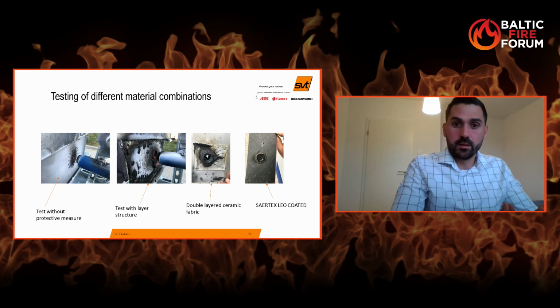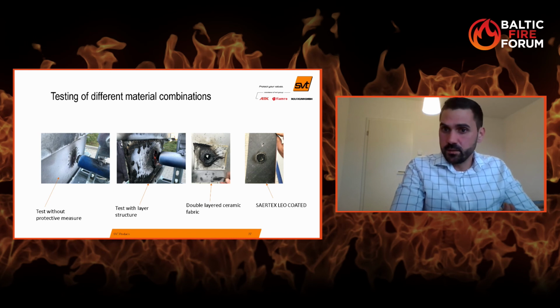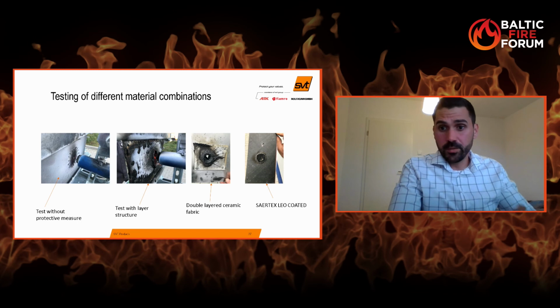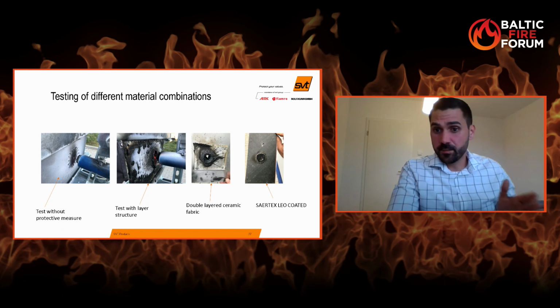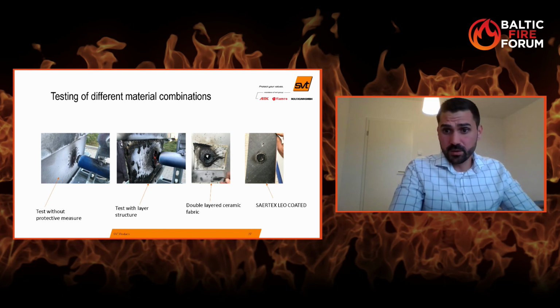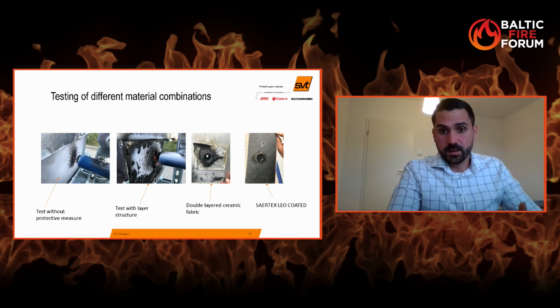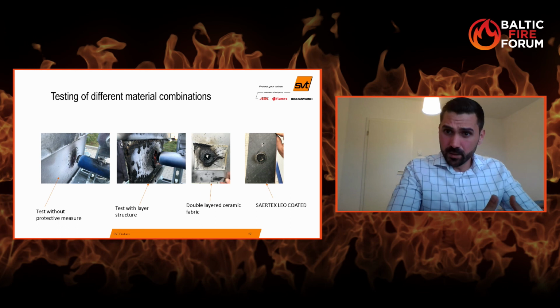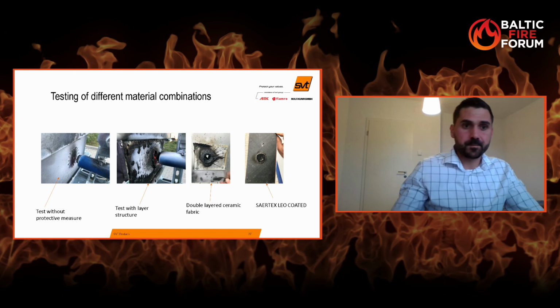And on the right side, you can see the material is SAERTEX Leo coated, as I already told you. That's about 3.5 millimeters, this plate, without aluminum, without any substrate, and the fire can't go through it, and they stop the impact for about 22 seconds. That's the time I already told you which the battery reacts, and we can achieve this goal with this kind of material. That's the reason why we keep our focus on this material in the area of battery safety, because we know it works.